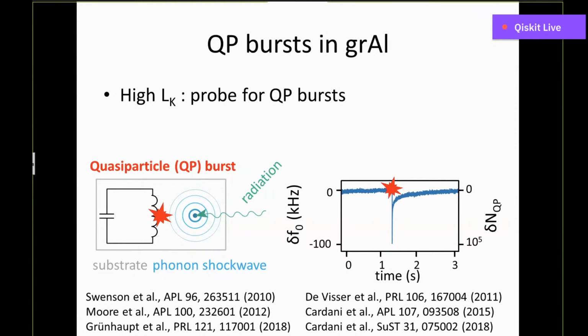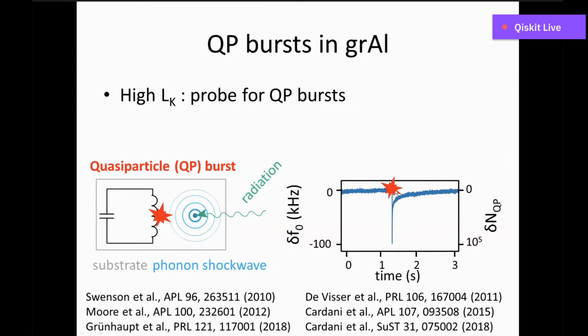And this will manifest itself as a drop in the resonant frequency of the superconducting resonator because of the increased kinetic inductance. We see here the shift from the unperturbed resonant frequency of a resonator over time. Once phonons hit the resonator and break many Cooper pairs in there, what I call a quasiparticle burst, then the frequency will drop and will then relax to the unperturbed values while quasiparticles recombine into Cooper pairs.